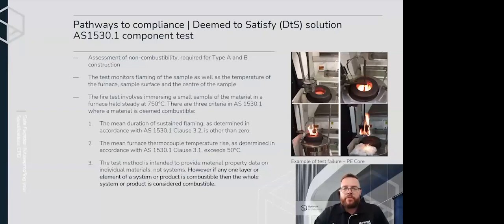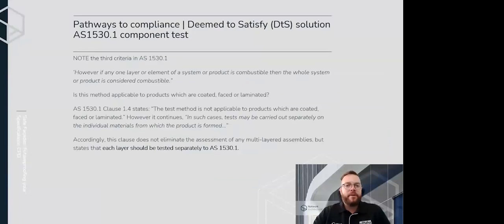The compliance of a material to the building code non-combustibility definition is determined by conducting an AS1530 Part 1 combustibility test. If the material satisfies the criteria outlined in the test method, the material is not deemed combustible. So this slide goes through what we've just covered off. However, down the bottom, accordingly, this clause does not eliminate the assessment of any multi-layered assemblies, but states that each layer should be tested separately to AS1530 Part 1.